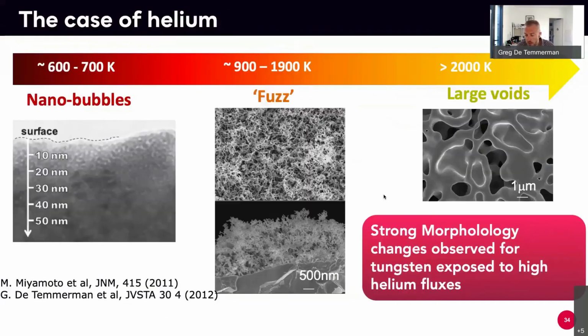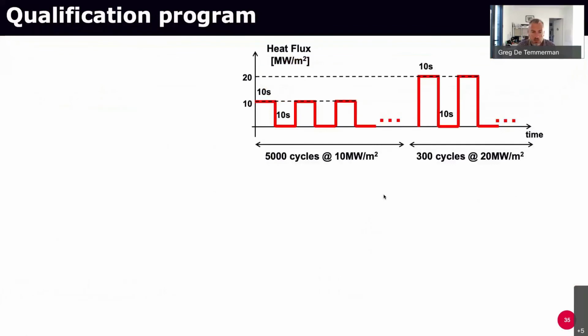And then the last thing I'll say, because I think I'm a bit short on time, is that in ITER, the plasma will be on for about 400 seconds, and then you will have to wait about half an hour for the machine to cool down and be ready for the next pulse. So you have a strong cycling of the surfaces, and every time you put heat onto the component, you have strong thermal gradients, and when you cool down, you heat again, and so on. So you have very strong cycling.